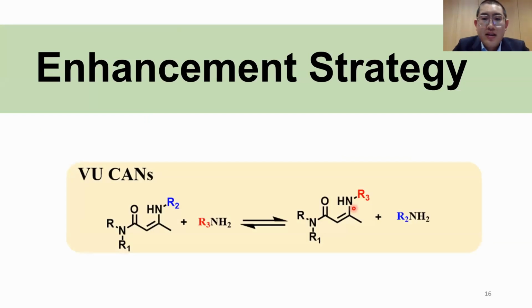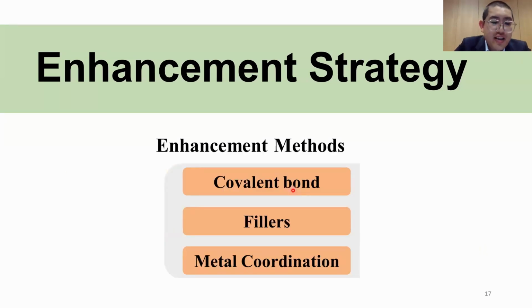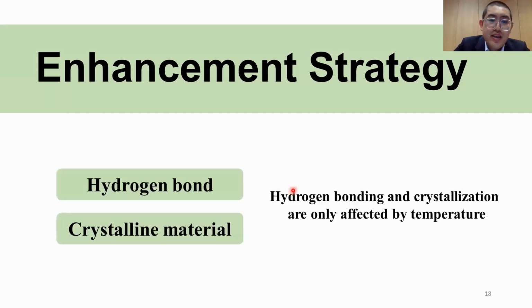Based on the performance, the vinylogous urethane CANs has a moderate exchange activation energy, the lowest mechanical properties, and the most significant creep at high temperature. So we chose the vinylogous urethane CANs for further enhancement study. There are many studies that have shown different ways to enhance CANs material, like covalent bonds, fillers, and metal coordination. But in our work, we select the hydrogen bond and the crystalline polymer, because both of these systems are temperature sensitive, so they will not affect the recyclability of the material.